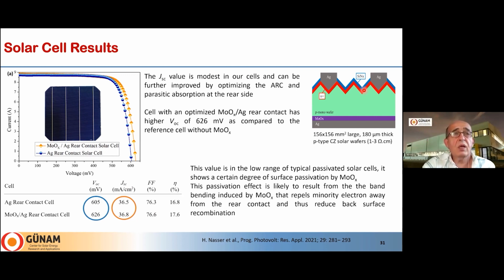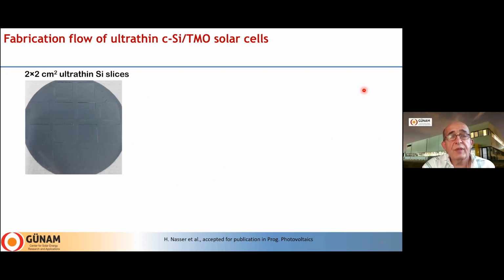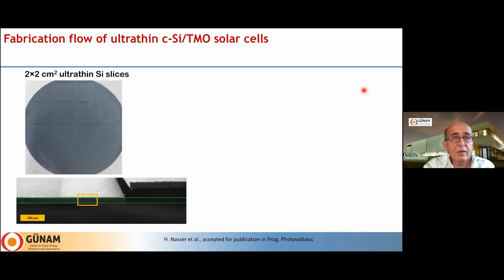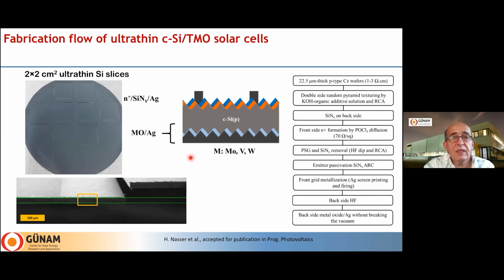And later on, we looked at the application on the ultra-thin crystalline silicon case. In this case, we obtained very thin silicon wafers by etching, and we obtained silicon pieces with a thickness of 22.5 micrometer, and we were able to process them in this structure, as you see. So each square here is representing a thin silicon region. In this study, we looked at different metal oxide layers on the backside. We looked at molybdenum oxide, vanadium oxide, and tungsten oxide.